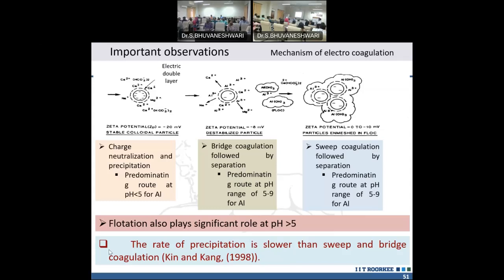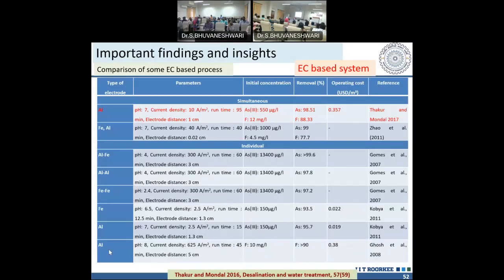And these are some EC-based systems, some examples. There are many researchers working on this, and this is our research also. So we see that at pH 7, current density 10 amps per meter square, runtime 95 minutes, electrode distance 1 centimeter, this is giving 98.51% removal of arsenic 3, which is at 550 microgram per liter, and 12 mg per liter fluoride, 80-90% removal. So the final water is below the permissible limit.